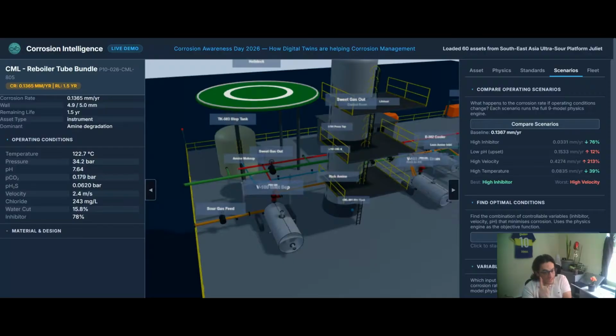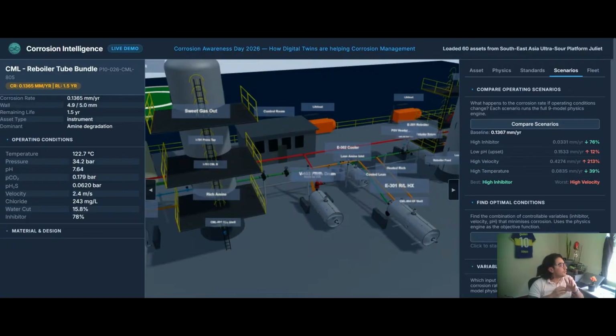So what happened if we have high corrosion inhibitor? For sure the corrosion rate is gonna go down, but the question always is by how much, by what percentage, how effective is our inhibitor, is it effective or not effective. So we compare against the baseline corrosion rate, and we can see here if we increase the inhibitor, we have the pH that is stable into this, and low pH for offset conditions can increase the corrosion rate. But the worst scenario on this asset we select will be high velocity, 213% increasing the corrosion rate. So it's a pretty cool feature that we can calculate how the asset is gonna behave between different conditions. Let's jump into the following one.